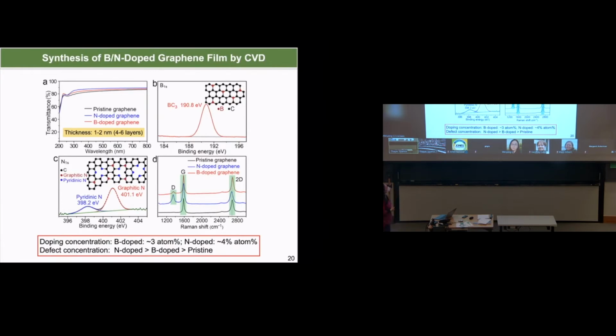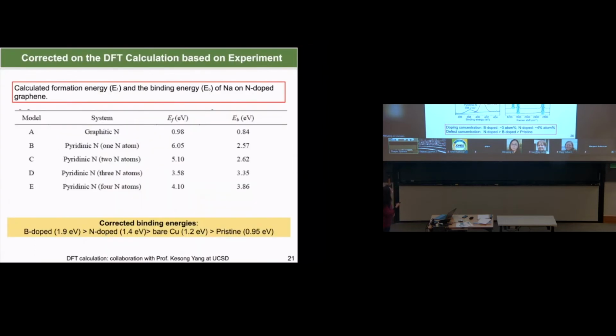But we do find experimentally, as you know, there are always differences between experimental results and theoretical calculations. For the nitrogen doped graphene case, you will see that it actually has different types of doping forms. So we had to make some corrections to the theoretical calculation to reveal the correct binding energy for the nitrogen doped graphene case. Here is our corrected binding energy. We found that boron is still the highest, followed by the nitrogen doped one, then bare copper, and then the pristine graphene case.